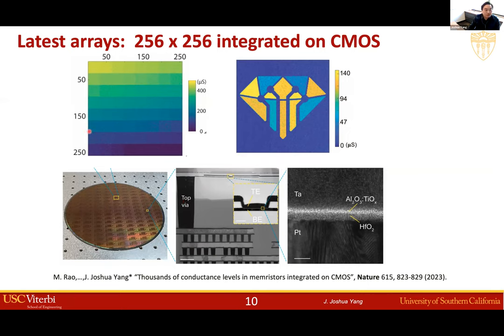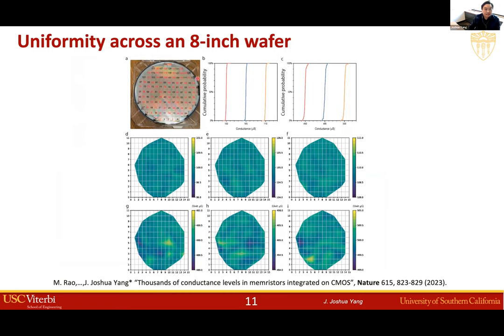And in the memristor array, each of the devices can be programmed analogically, using the on-chip driving circuit, as shown here. Those are the experimental data of programming the entire array with a very, very high yield. And the uniformity across the entire wafer is extremely good, as shown here. The very narrow distribution of device programmability across the entire wafer. In fact, I have some of the wafers shown here.